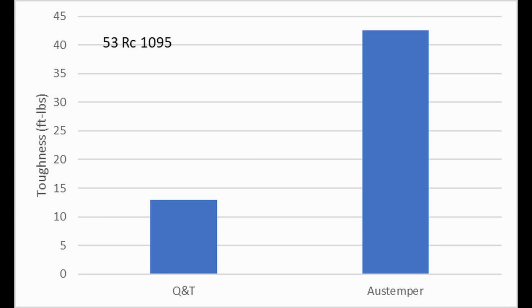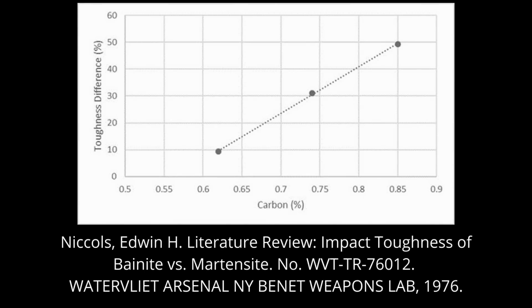Now, another thing on the subject of plate martensite versus Bainite is here is a chart. It's a percent toughness difference between tempered martensite and bainite for different carbon contents. And you can see that as this line approaches the 0.6% carbon or so, where there is all lath martensite and no plate, the toughness difference approaches 0 between bainite and martensite. So they have the same toughness at lower carbon contents. At higher carbon contents, the toughness difference becomes bigger and bigger, and the bainite has more and more of an advantage.